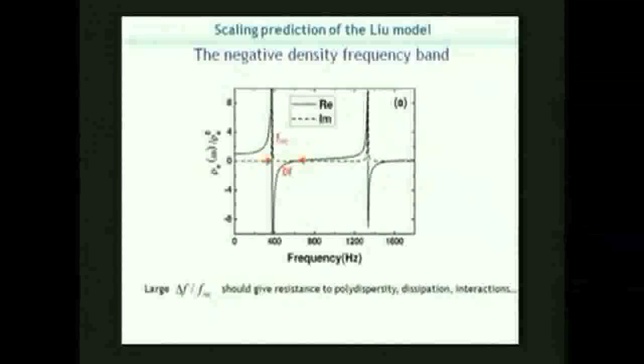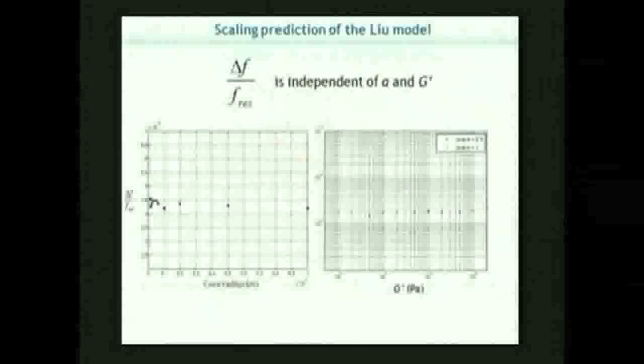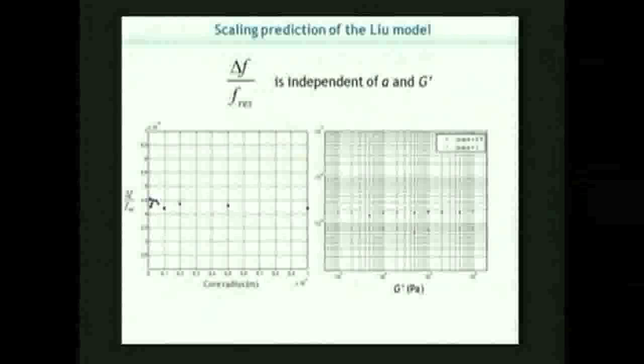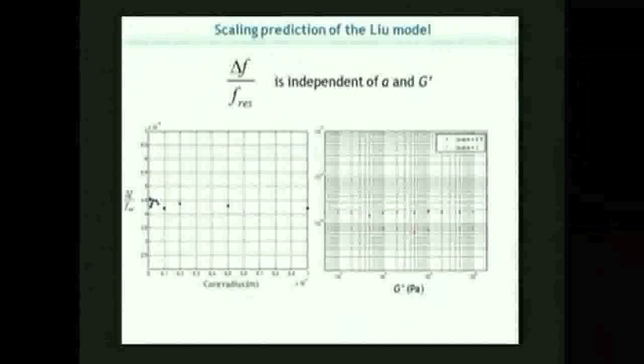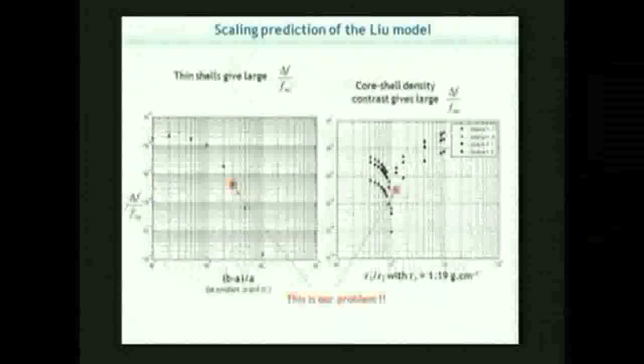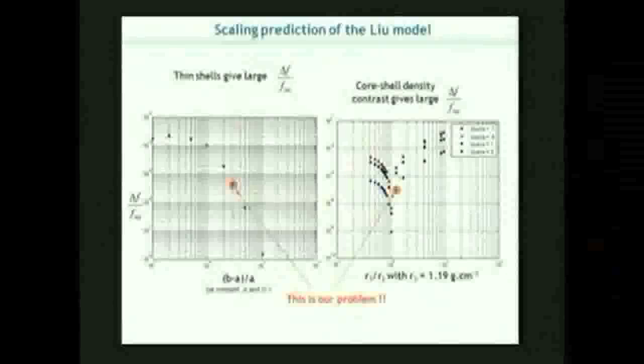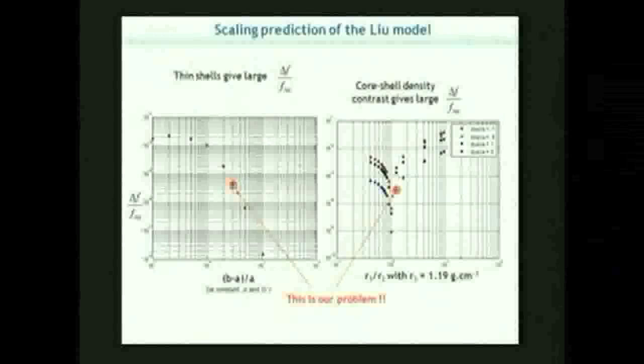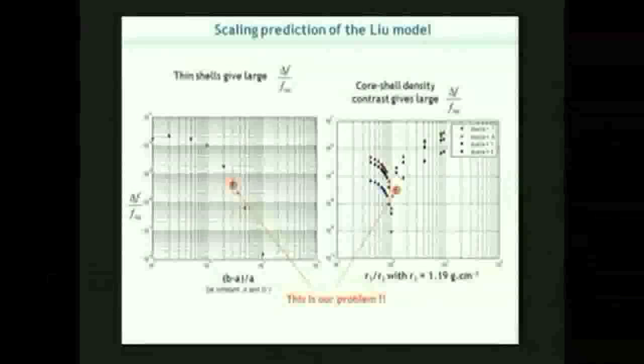And so we try to calculate the evolution of this, I would say, negative window, as a function of the different values of the system. So we see that this width of the negative window is independent of the core radius and is independent of the value of G prime. Okay? But a problem is that this value of the window, the negative window, is very strongly dependent on the ratio of the shell thickness divided by the core radius.